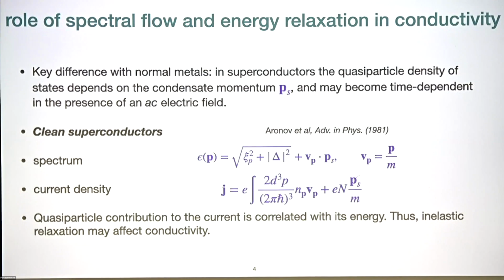Boris already did the introduction, but maybe one way to illustrate how the inelastic relaxation time can appear in the presence of a condensate momentum is the following. If you consider the clean case, then the energy of a quasi-particle acquires a correction proportional to P_S. This correction depends on the normal state velocity of the electron, and the contribution of the same quasi-particle to the current is also proportional to the same velocity. This tells you that the quasi-particle energy and its current become correlated, and therefore current relaxation becomes intertwined with energy relaxation in the presence of the superfluid momentum. And in the mixed state, superfluid momentum is naturally present due to vortices, so we may expect that the inelastic relaxation time will appear in the conductivity.